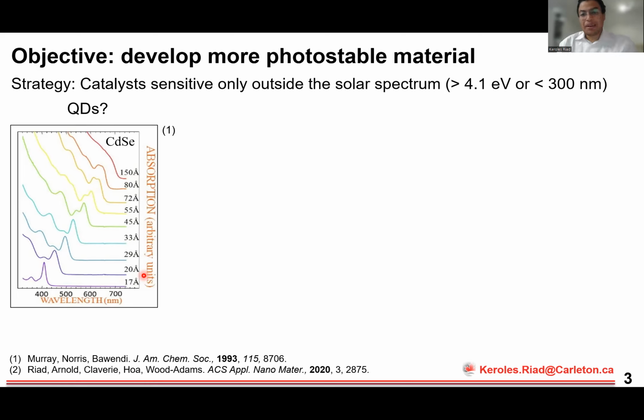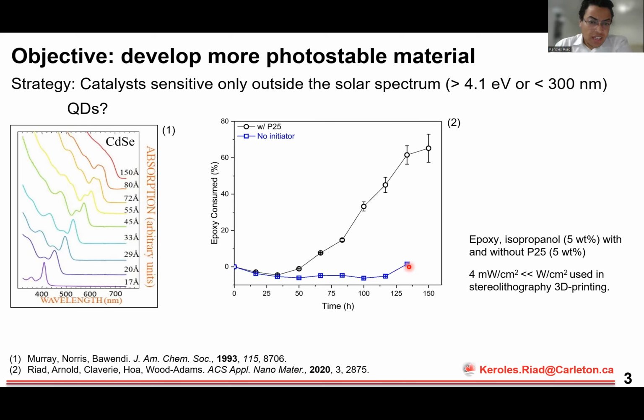And so the first step for my research was to actually demonstrate that semiconducting nanoparticles can do the chemistry, can do the photocuring, because up to that point, it had not been shown. And so early in my PhD, this is what I did. And in this graph here, it shows the epoxy consumption, which is a measure of the photocuring reaction kinetics, as a function of light exposure time.